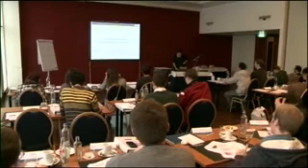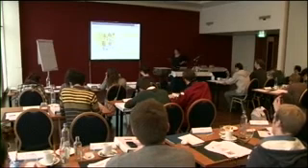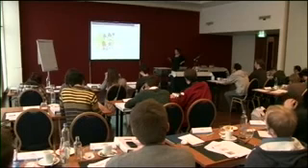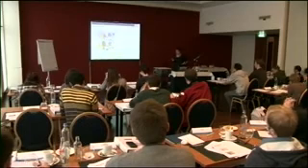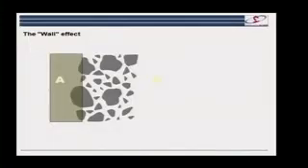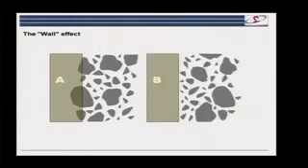Concrete, we have aggregates. And we know that the microstructure around aggregate is not the same as in the bulk cement paste. And the reason it's not the same is for this very simple reason. Here's a cement paste. If we put an aggregate there, the grains can't be cut by the aggregate. You know, they're physically pushed out of the way. And this is what's called a wall effect, where we tend to find fine grains in this region here and larger grains further out. And the consequence of this is that the porosity, the free space here, is higher right against the wall than out here.